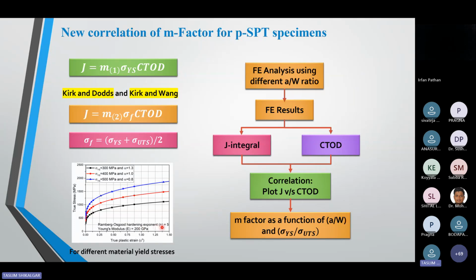I varied it from 5 to 20. So I generated first the database input material property, true stress versus true plastic strain data, and I used one data set for one simulation. So I generated almost 15 to 20 curves, and I ran these simulations, like FE analysis, for different a/W ratios. For that purpose, I decided to use only 3 a/W, 0.4, 0.45 and 0.5. So I used 15 true stress versus true plastic strain curves and 3 specimens, to total 45 simulations.